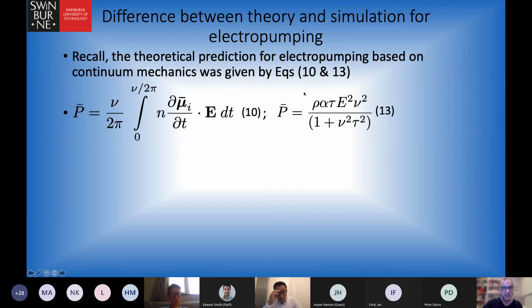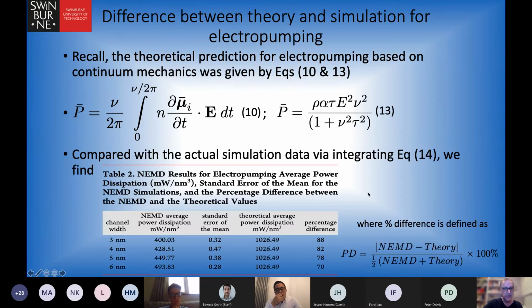Now, if you recall, this was the expression that Bontuis and colleagues derived for the average power from pure theory. It didn't take into account the inhomogeneity of the system. How does that compare with the actual numerical results we get from our electropumping simulations? So this is what we actually measure in our NEMD simulations for various channel widths. And this is the theoretical value, which, as you can see, is just a single value because it doesn't take into account the degree of confinement. So certainly for the narrowest channel width, we've got a difference of a factor of about 2.5.